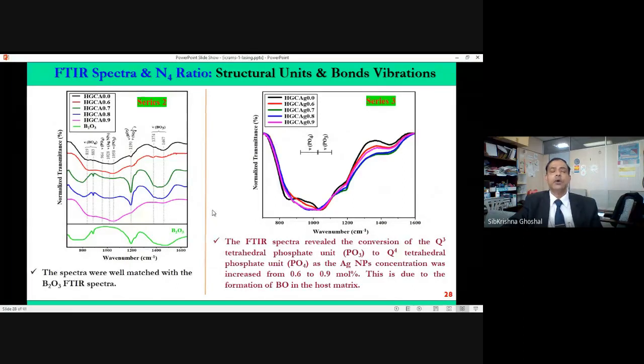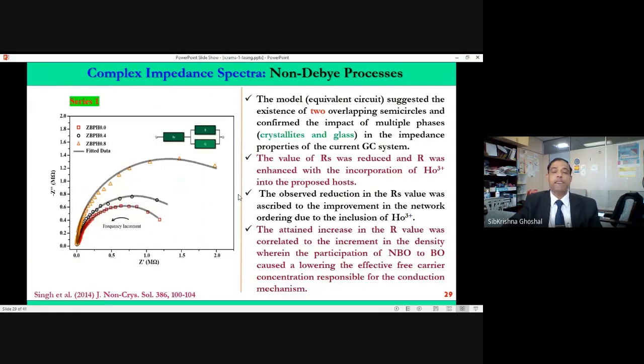The second issue, whether we have formed the right structure or is there any impurity, is there any bad elements in the structure? No. Go for FTIR analysis, look at the spectral weight, and from those weights, we can clearly find the concentration of those units, and then we confirm that they are there in the system. Then we could do the impedance spectroscopy to look at the source of polaron or bipolaron physics.